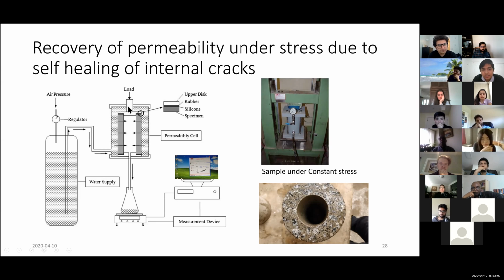The hollow cylinder is sealed from the top and from the bottom, and the water fills the outside zone. So there is water around the sample. As we pressurize it, the water has to pass through the sample radially inwards, and the water drips out from below, and we can collect that in a beaker and measure the weight. After measurements in the computer, we can observe the rise of weight versus time.